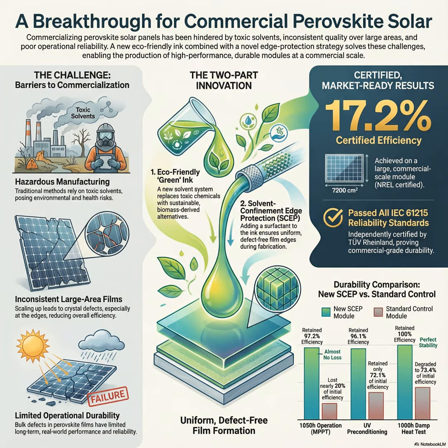material. Exactly. The researchers confirmed it. They created void-free, high-crystalline, defect-minimized perovskite films. They solved the toxicity problem and the core material quality problem at the same time, at least on a small scale. Which brings us right to that second barrier, scale.